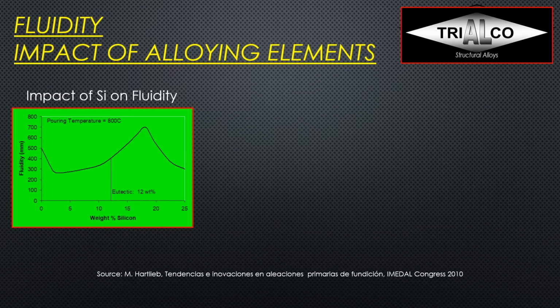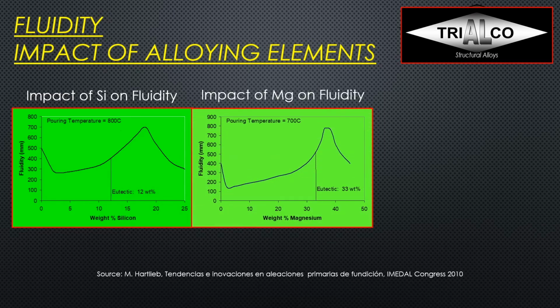And at the eutectic point, I have recovered very good fluidity already, but if I wanted to have the best fluidity, I would actually go to an 18% or so silicon level, which is exactly what we see in the typical hypereutectic alloys of the 390 family.